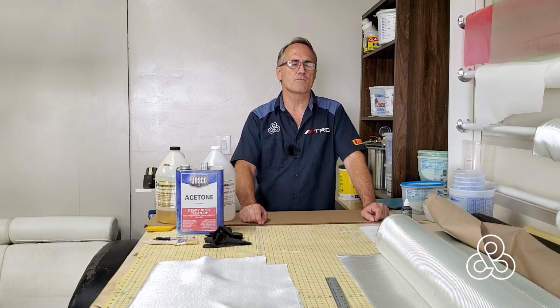But the mat and some of the fiberglasses have a binder in them that holds the fibers in place. And when you're using epoxy with mat, it is just a real disaster, because the epoxy is so slow at breaking this binder down that you have less work time to really get the mat into position. Whereas the binder is based on a product that is broken down really easily by styrene. And styrene is one of the components of the ester resins. So when you put the vinyl or the polyester resin on a mat, it quickly breaks down the binder, and the mat is able to conform really quickly as it's able to slip and slide those fibers around and get into position.